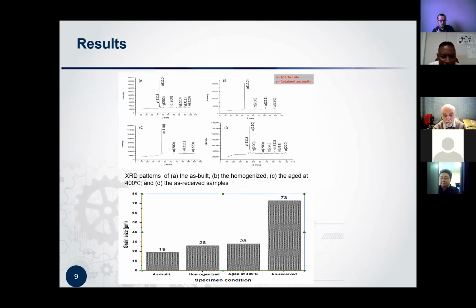Another interesting thing that we did find, if you can see, these are XRD results. If you look at the XRD patterns for D and C, C is for the optimum aging condition, or the modified H950 condition. You can see that we managed to get rid of the retained austenite, or we managed to suppress the retained austenite. Whereas for the as received sample, the austenite is there. Now this is important, especially for engineering applications, for a component that undergoes mechanical loading. Remember, retained austenite is a metastable phase which tends to transform into brittle martensite upon loading. So it's good that the one we produced doesn't have retained austenite, but it can still have elongation.